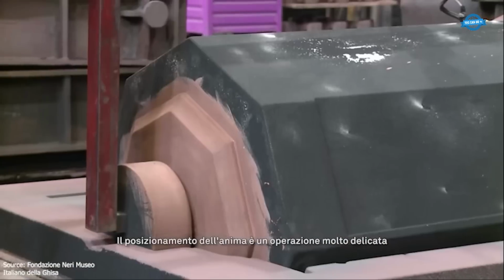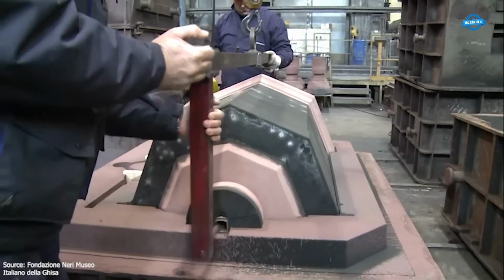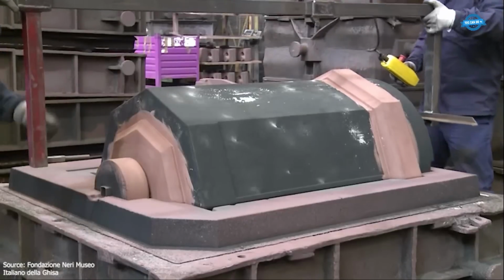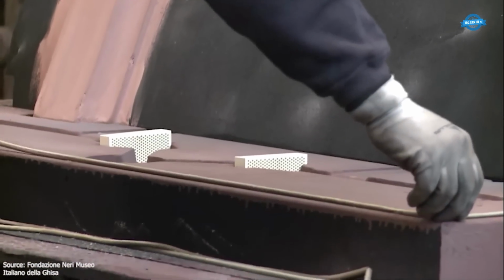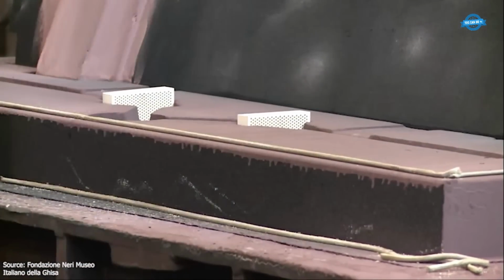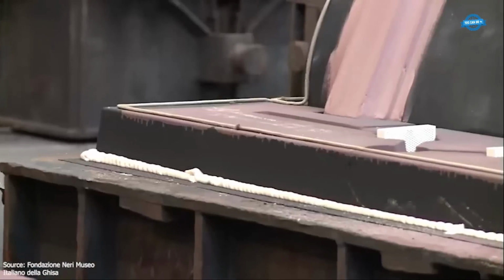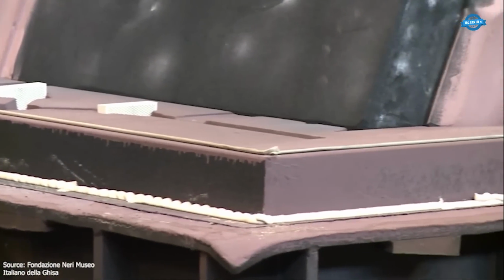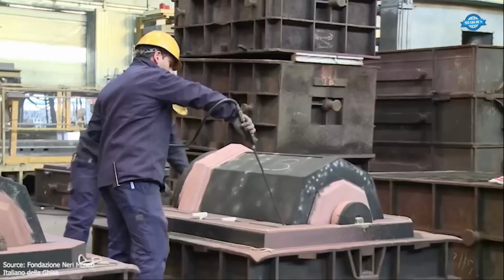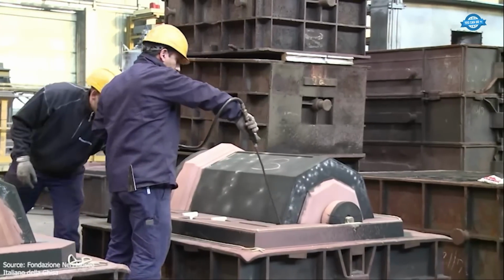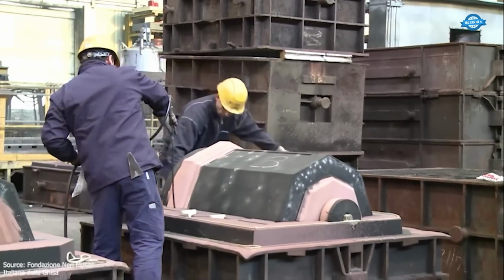Once applied, the coating is dried in an industrial oven to ensure it adheres evenly. The two mold halves are then positioned side by side. Into the bottom half, the core is placed. This core is essential in forming the internal cavity of the cast component. It is slightly smaller than the desired cavity by about 1 centimeter on all sides, which determines the final wall thickness of the cast iron part.